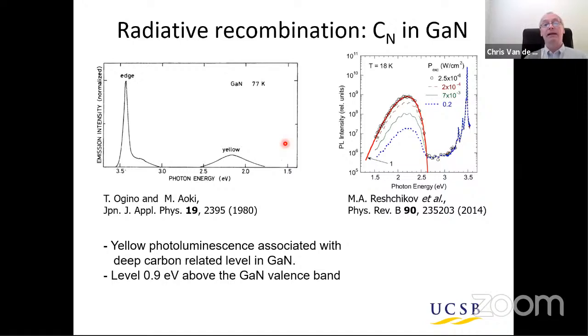Okay, and I wanted to choose a specific example which we've used as a benchmark because it has been so well studied, and it also illustrates the power of doing these calculations for actually identifying the source of optical emission that is experimentally observed. Okay, my example is carbon in gallium nitride. 40 years ago, there were already experiments that showed that in almost all gallium nitride, you see yellow luminescence, a broad luminescence band centered around 2.2 eV that is almost universally present.